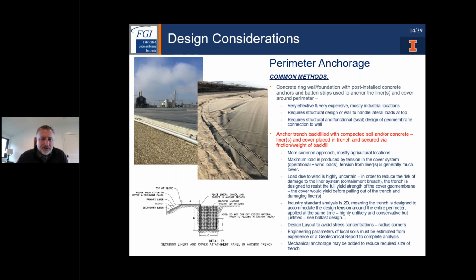More commonly, and what you mostly see in agricultural applications, is an anchor trench, a soil anchor trench backfilled with either soil or sometimes concrete added for weight. This system is usually designed so that the liner and the cover system are both included in the same anchor trench. But the cover system produces significantly more tension due to the operational pressures and wind load than the liner system. And so that's where we typically have to design the trench sizing to accommodate the cover system.